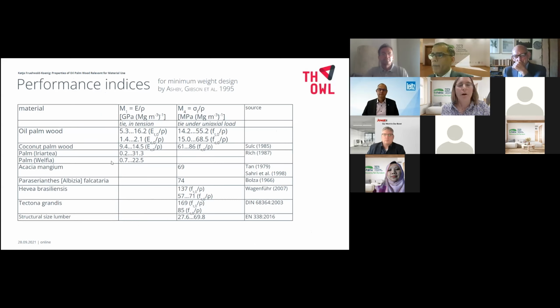Because of the power law relationship between the Young's modulus and the density, the performance indices for a minimum weight design by Ashby calculated for oil palm wood are rising with the density. The specific strength M2 of oil palm wood is lower than the values for small clear wood test specimens, but in the range of structural size softwood lamellas. The specific modulus M1 and tension are in the lower range of common wood species for high density palm wood. Next slide.